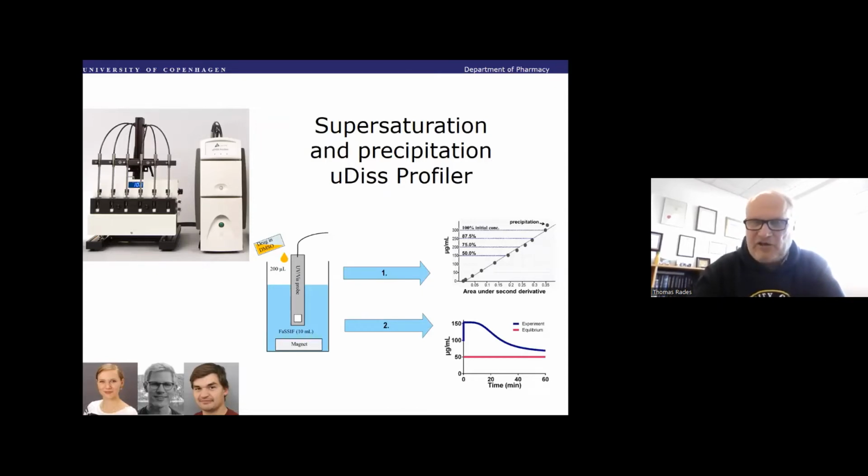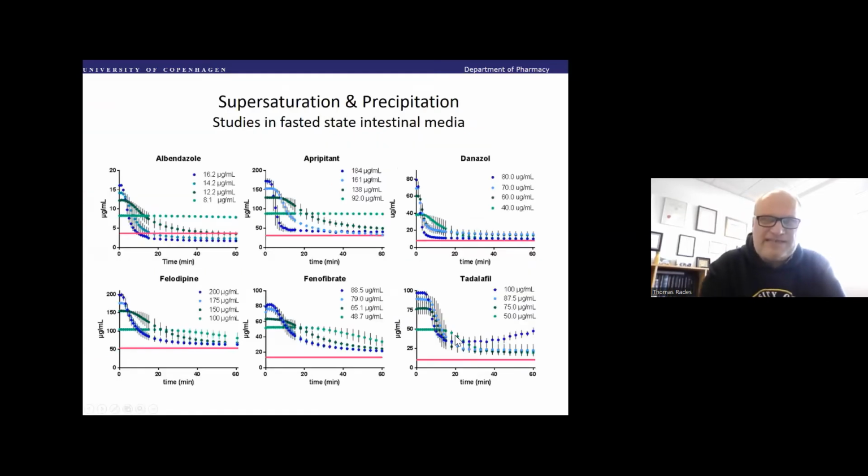And then we are getting curves like you can see here below, where the drug stays in solution for some time and then it crashes out. And if we do this at these 4 concentrations that are now, so to speak, normalized for all drugs against their maximum ability to contain drug, then we get curves like this, where we see that with increasing concentration of drug that we add, the induction time gets shorter, and then crystallization or precipitation occurs.